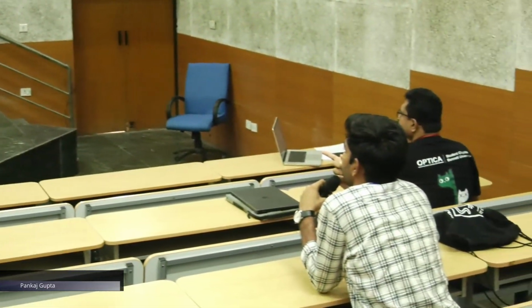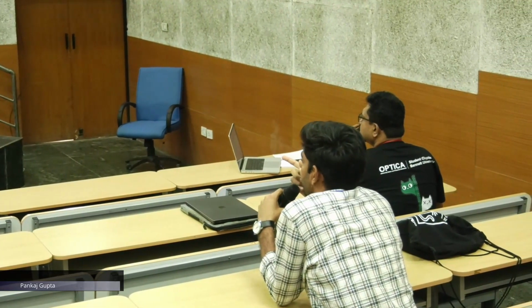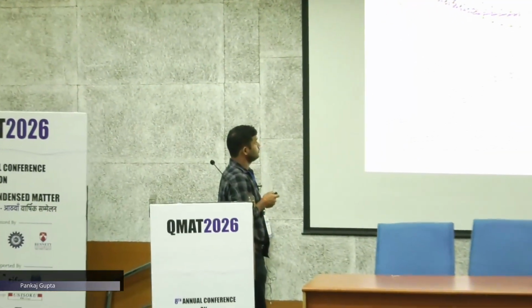So in one of the slides you have shown that with an increase in the Z component there is an increase in conductivity. A systematic study there was. Yeah, this one. But the sigma value of the conductivity increases at 5 and then decreases. Right. So 8.5, then for 10, 15, 17.5 and all this, it is reducing. Why the sharp increase at Z equals 5?